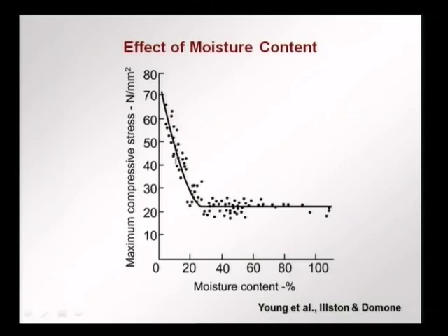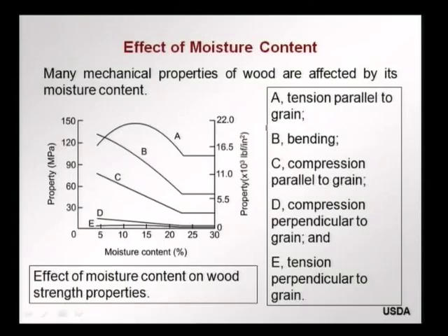So, this is what we want to achieve by proper seasoning, and this we find in many other properties also. This is a graph from the USDA document where we have different properties such as tensile strength parallel to the grain, bending strength or modulus of rupture, compression parallel to the grain, compression perpendicular to the grain, tension perpendicular to the grain. We find that in all the cases we have a decrease in the property as the moisture content increases.